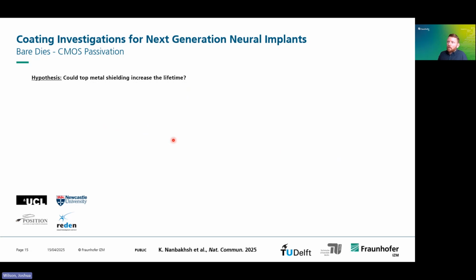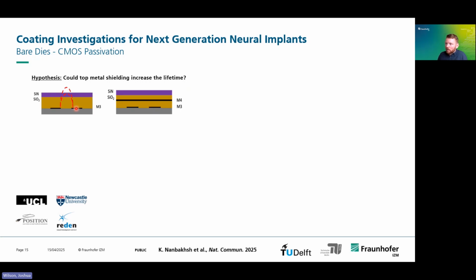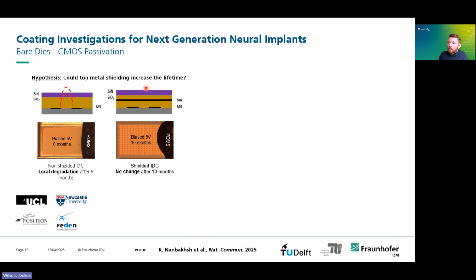So how can we improve this? One hypothesis is to introduce a shielding layer. What I mean here is that in the devices that degrade, we have these two metal lines in black, and we have an electric field that passes between them. And this stray field can reach out into the body fluid, and this can drive some degradation process. But if we introduced an additional metal shielding layer, all these field lines would terminate here, and there would be nothing to drive this process on the surface. And in fact, what we see is that if we use this shielding, there is no change on the surface of the silicon nitride in comparison with the other devices which didn't have shielding.